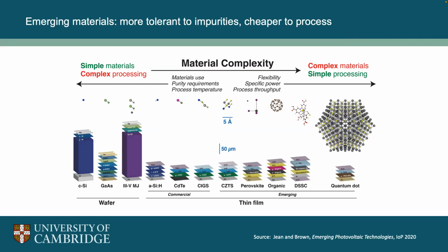These get much more complex. When you think about the structures and the disorder in these materials, they are more complex. But generally, the trend is that these are simpler to process. So they can be much cheaper, but generally they're lower efficiency because they are more disordered. Whereas here, these are much more complex to process, but they are simpler materials. And so what we ideally want is something that can perform really well, but is simple to process and cheap.